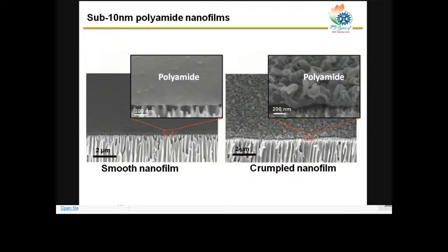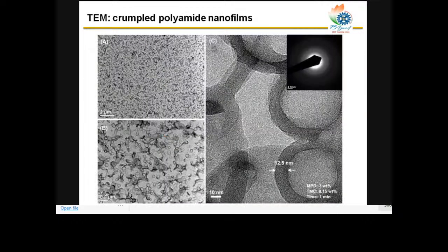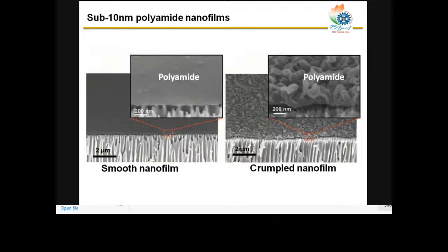So using this method, we can actually make polyamide nanofilm of two different physical structures. One is smooth polyamide nanofilm on the left, and on the right is shown a polyamide structure with a crumpled nanofilm. So depending on the smoothness or crumpledness, we can have a different surface area of the film. Obviously, on the right, that crumpled nanofilm will give you higher permeable area because it can access much more area compared to a smooth film. So the smooth film will have an area only proportional to the support. However, crumpled nanofilm will give you much higher area than the porous support on which it is made.